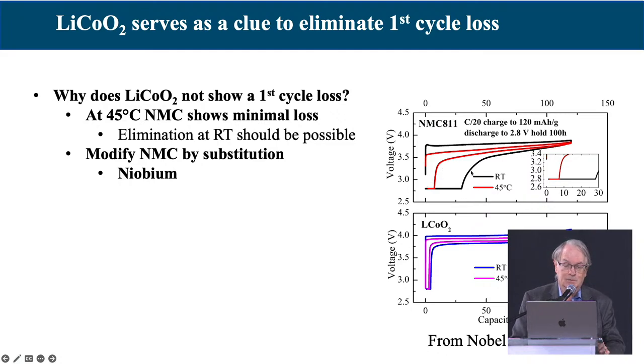The black is at room temperature, and we held it for 100 hours at 2.8 volts. You can see all the lithium eventually goes in, clearly kinetics. The red one is at 45, it's almost all gone back in. Lithium cobalt oxide, there's no first cycle loss to speak of. So we said we're going to modify the material so this oxygen doesn't tend to go out, and also hopefully so we can get the kinetics better.